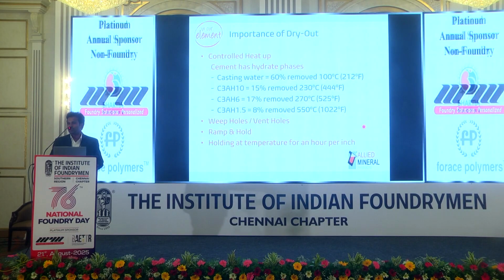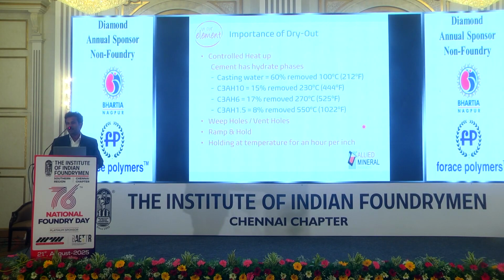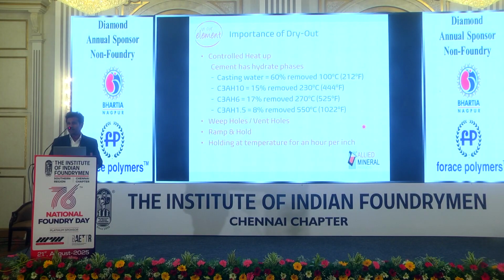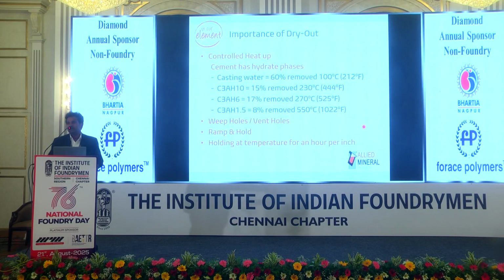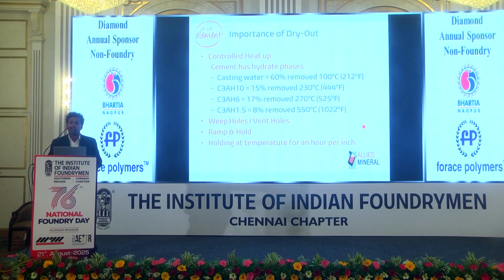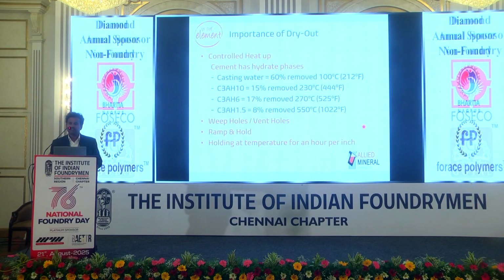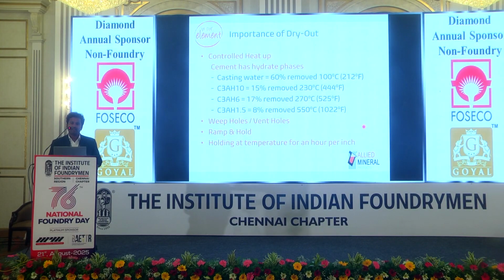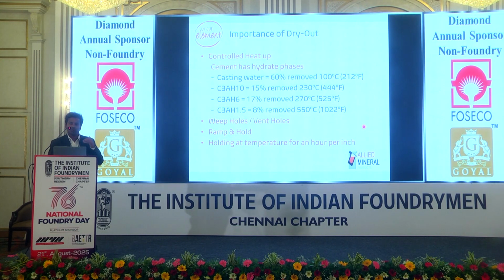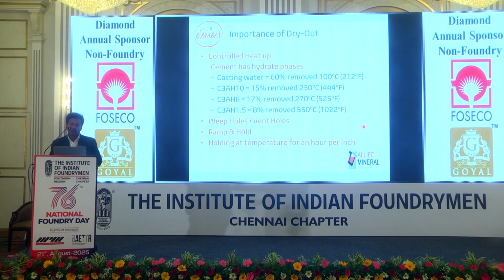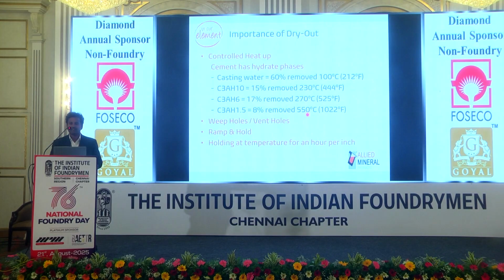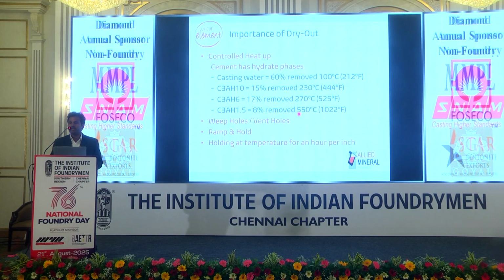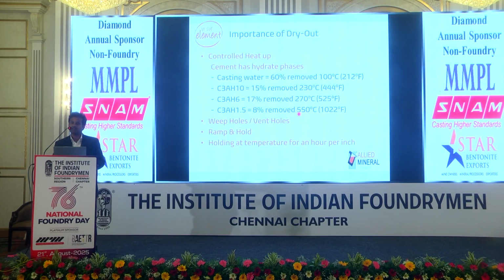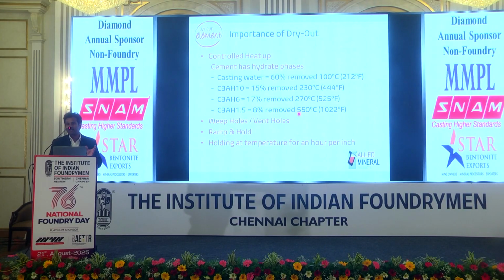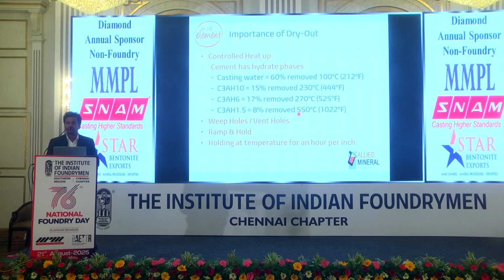Traditionally, people used wood firing and other systems, but that is not sufficient to drive out all the moisture. When water is added to the cement, it forms hydration phases. So complete chemical moisture will come out only after 550 degrees Celsius. So your ladle has to be heated to a minimum of 550 degrees Celsius, and according to your lining thickness, this ramp and hold system has to be designed.